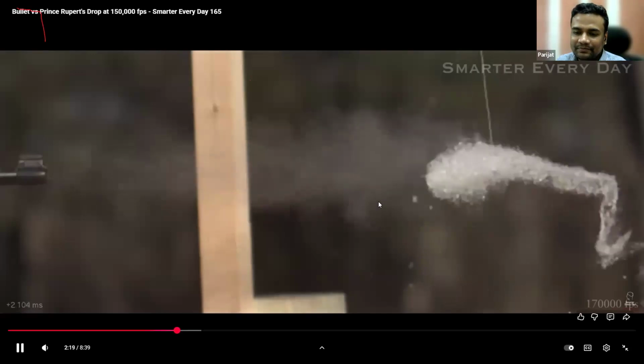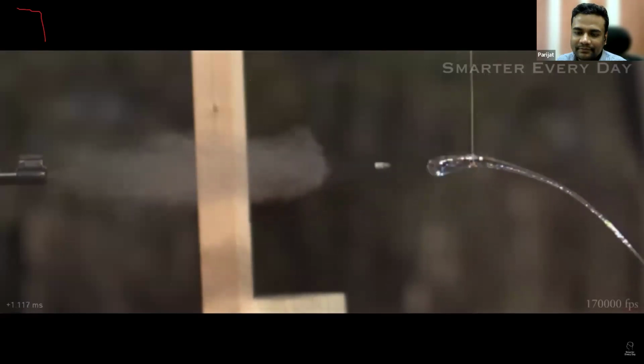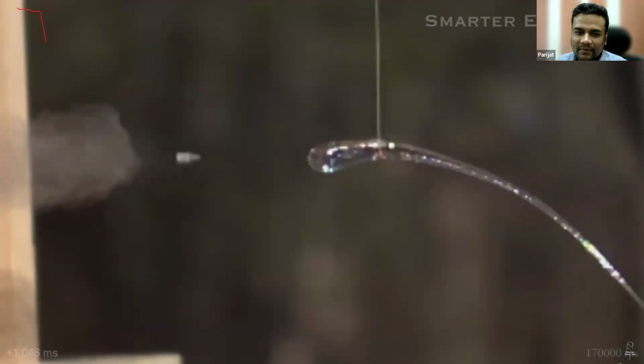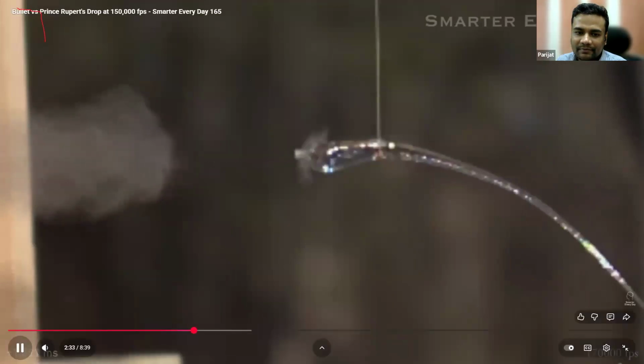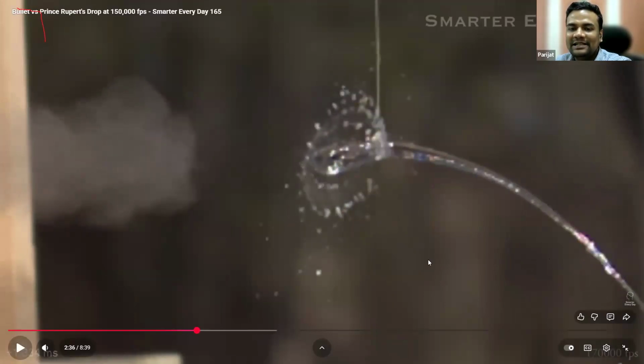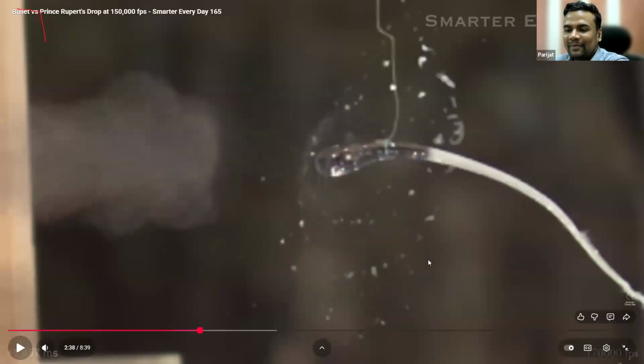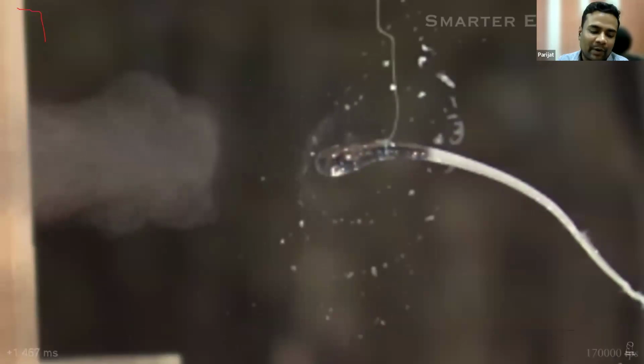But if you see the initial impact of the bullet with the glass, you see that at that time the bullet got fragmented. This is so high strength. But the crack started from the lower end, the bottom end, and propagated and shattered the glass. But at that time it remained intact, and the bullet got fragmented. So you can think of the strength of this one. Now how the crack from the bottom propagated. That is the drawback of glass: once a crack propagates, it propagates very fast. It does not have any microstructure obstacle to restrict the crack propagation.